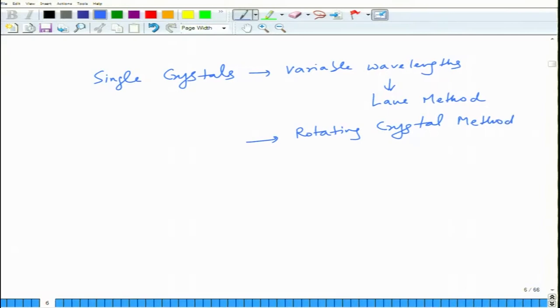In that method again, the wavelength is fixed, so it is a fixed lambda, but the crystal rotates. So you have a crystal which undergoes rotation, and this is the incoming beam of fixed lambda. However, in case of polycrystals, let us say powder specimens, where every plane is randomly oriented in space, you have every possible orientation available to the incoming X-ray beam.